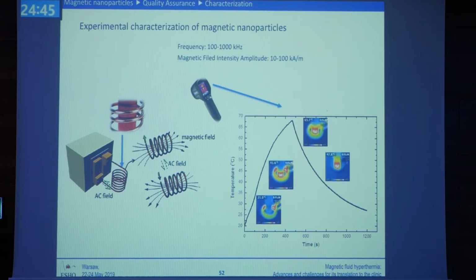You can see here when the coil is conducting current, that creates an AC magnetic field along its axis. You can see the increase of the temperature because of the release of energy from nanoparticles. And I repeat here, perhaps I will tire you, that there are two ways of releasing energy, either with Néel relaxation or with loop hysteresis. So they can be either superparamagnetic or ferromagnetic, the iron oxide nanoparticles.